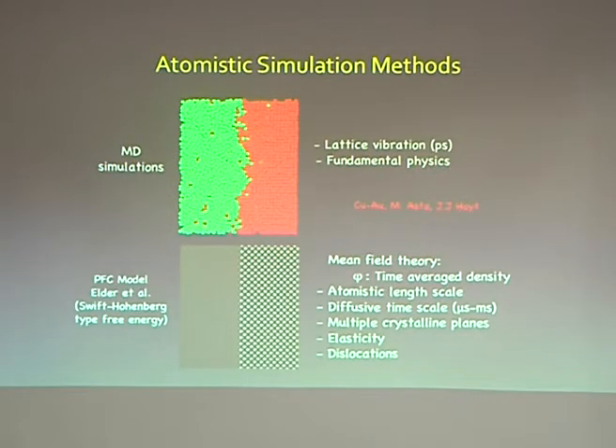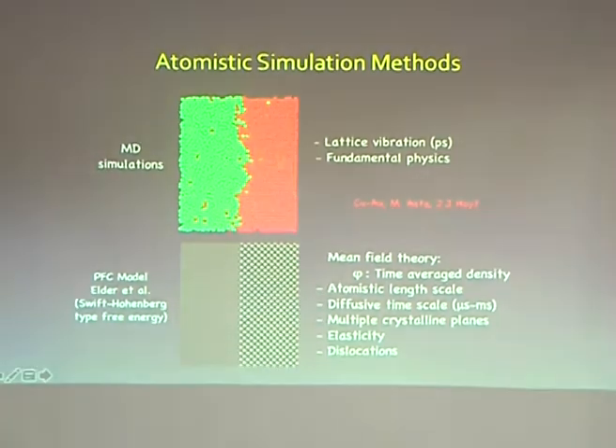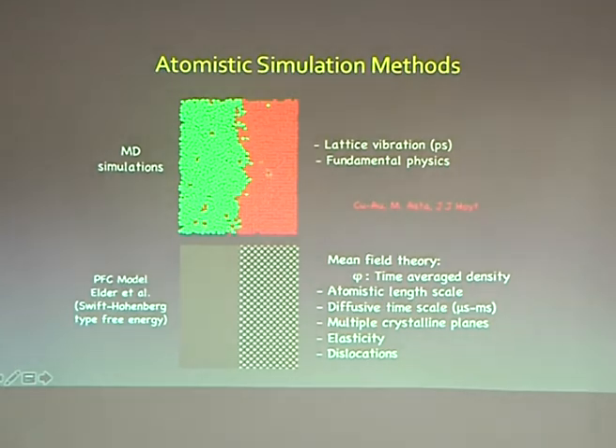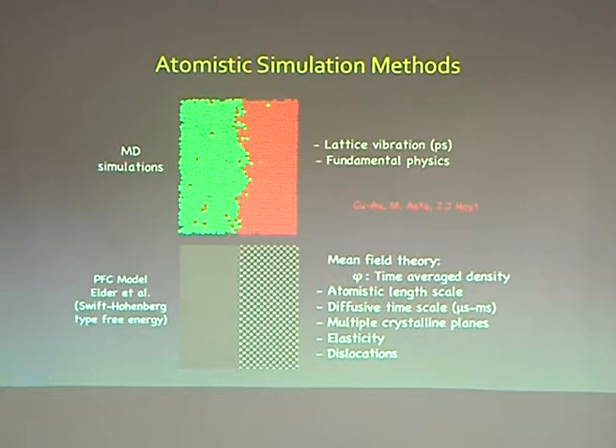What is the motivation for phase field crystal models? If you look at classical molecular dynamics simulation — this is from Mark Asta and Jeff Hoyt — this is a molecular dynamics simulation of copper gold, showing the liquid as highly disordered and the crystal quite ordered. These simulations occur on lattice vibration time scales: picoseconds, femtosecond time steps. A massively long molecular dynamics simulation will reach about a microsecond. However, typical materials evolve over much longer time scales, and the problem from the molecular dynamics community has always been: how do you get around this lattice vibration time scale?